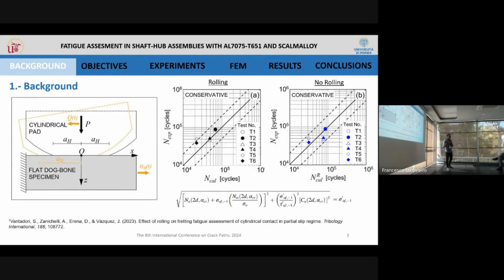Also, in a previous collaboration with our colleagues from Parma, we studied the cylindrical contact pair subjected also to fretting, and we included the rolling effect. The important thing here is that we applied the well-known Carpinteri criterion to try to estimate the fatigue life of this assembly, obtaining very good results, taking into account both rolling and no rolling. This is the point at which we wondered if we could apply this criterion, that is a stress-based criterion, to our shaft-hub assembly and also include the Scalmalloy.